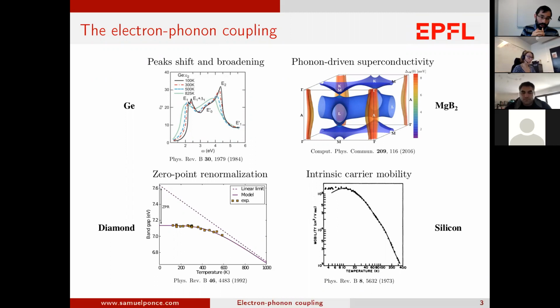And so this means you cannot describe very important phenomena, such as the peak shift and broadening of absorption spectra, and phonon-driven superconductivity. The BCS theory is purely based on electron-phonon coupling. The zero-point renormalization, but also the temperature dependence of all the eigenstates and the band gap as a function of temperature. The mobility, so the carrier scattering. This is, again, directly the reduction of mobility with increasing temperature. This is, again, a direct manifestation of electron-phonon coupling.